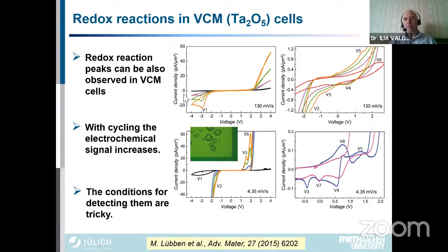So you see, after the initial sweep here, in the one VCM device. The initial sweep is almost no current. Simply sweeping, you see that the current starts to increase, and this peak here is indicating the electrochemical reaction. If you zoom in on more details here, you see the electrochemical reactions happening. And if you continue with cycling for more time, you see also bubbles from gas that formed.